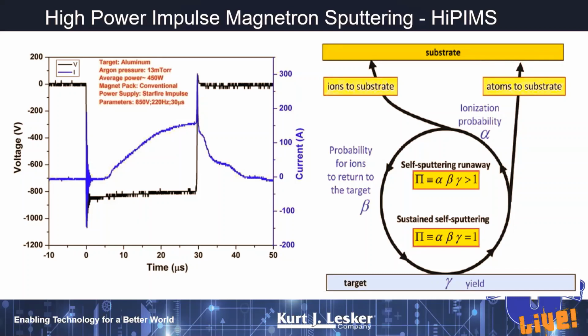But by having this massive pulse here, we're going to create lots and lots of target ions, now sputter target ions. And some of those sputter target ions will make their way to the substrate, and that additional energy will help contribute in the formation of a dense film. But some of those sputter target ions will now circle back to the target, and we'll start now sputtering the sputter target with sputter target ions, and that's called self-sputtering.